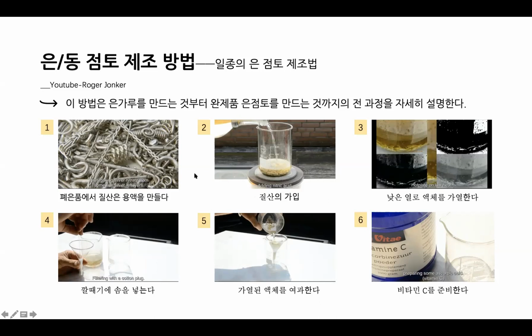Next step, pour a small amount of water into a beaker and then add methyl cellulose to the other. Then mix the solution, water and methyl cellulose in another beaker to obtain the mixed solution. In order to better integrate the solution, the mixed liquid can be placed in an ultrasonic cleaner and then add some reducing agents, which is vitamin C. Gradually, it can be seen that silver ions are reduced in solution and form fine powder. Pour the reduced silver powder into the funnel and the filter, and wash the silver powder with DI water. At this time, we can get fine silver powder.